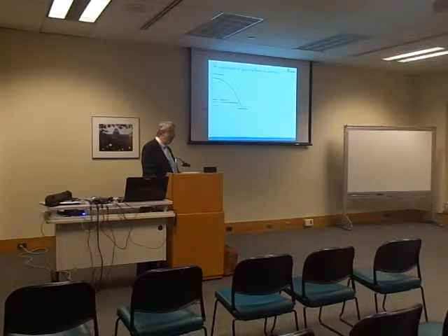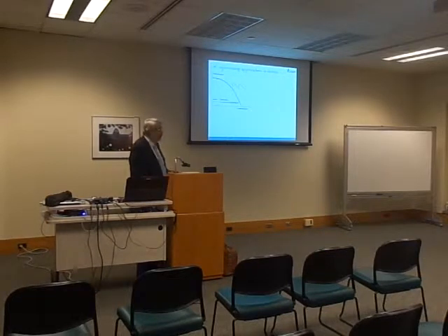So you are assuming there is a correlation between the loss in aggregates and the complex moduli. But as the aging occurs at the beginning, there is a stiffening of the material that apparently improves the property of the material, reaches a point, and there is a complete degrading of the material. So until you reach that point, you might not have much loss of aggregates.